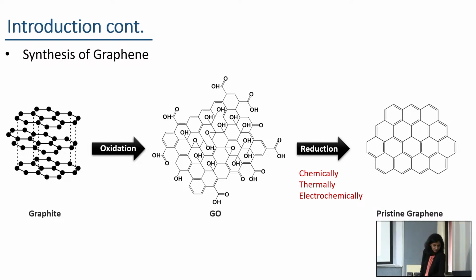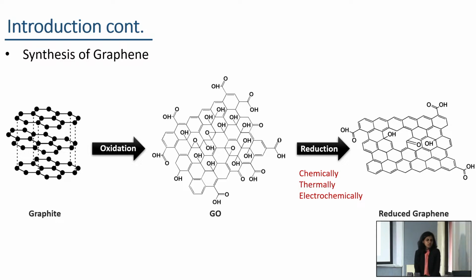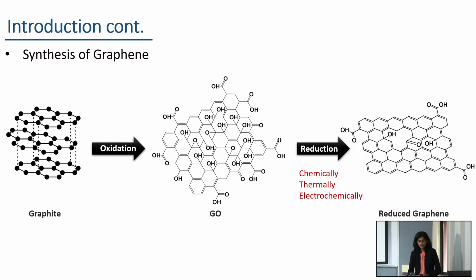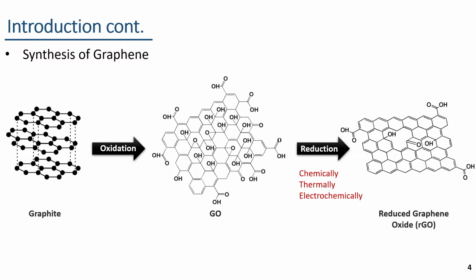Therefore, instead of that, a graphene-like material that is referred to as reduced graphene oxide, which is RGO, with residual oxygen functionalities and basal plane defects is typically obtained during this reduction process. Here the properties of reduced graphene oxide as well as graphene oxide highly depend on the structure of graphene oxide.